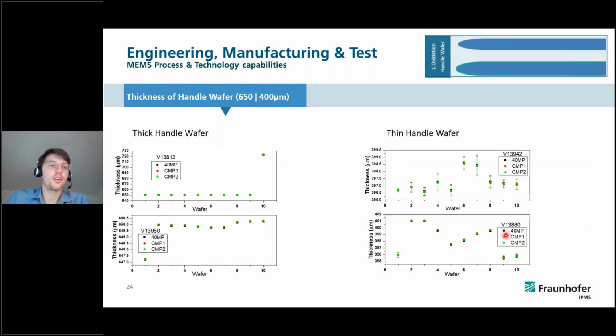And what we did first of all was measuring the thickness of the handle wafers, preparing the handle wafers, and getting the thickness done for the handle wafers, because you have to make sure that you know the value of each wafer. As you can see, there are deviations in the thickness of the wafers all over the board, and when you grind back to a target thickness, you need to make sure that you only grind as much as the difference between the given number and your target number is.